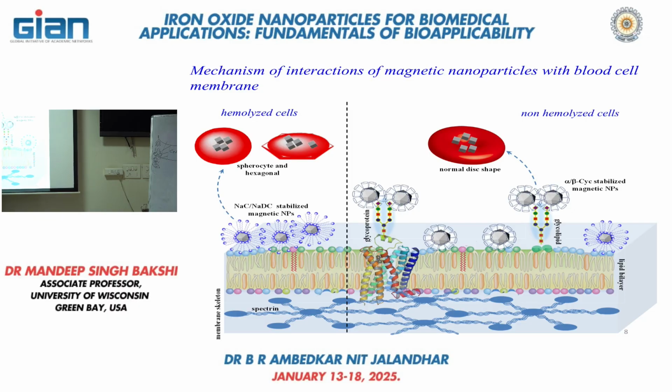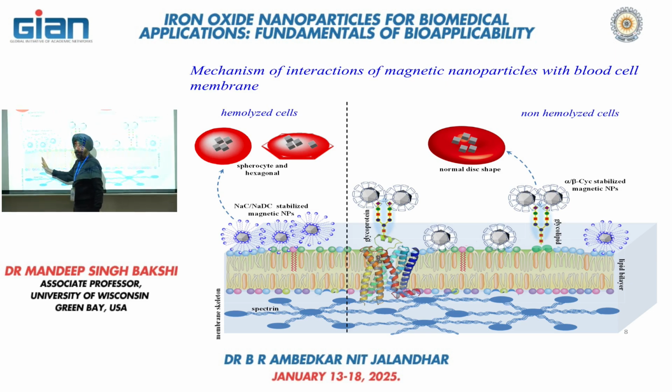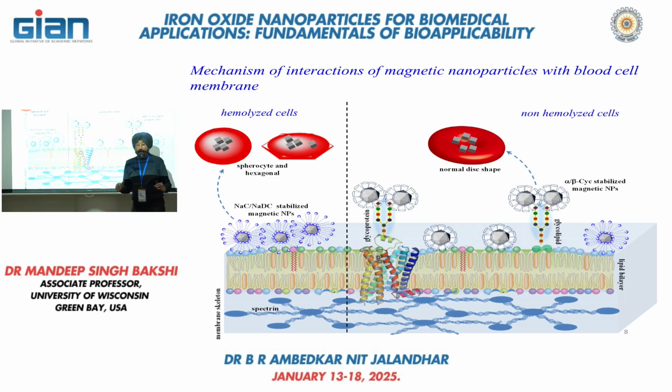And therefore these nanoparticles, which are coated with the amino acids, or even the biological surfactants, are not working. They have the ability to break the cell membrane, so we cannot use them for the extraction of blood cells. It means that these magnetic nanoparticles, which are produced with various kinds of amino acids and the biological surfactant, are not good magnetic nanoparticles for extracting the blood cells. But what is good? Cyclodextrin.